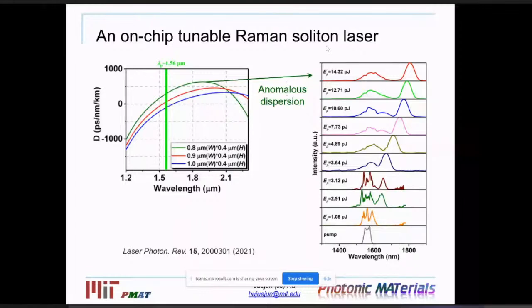And what happens here is that this ultra-short femtosecond pulse, when it couples to the waveguide, because of the large light intensity, starts to trigger stimulated Raman scattering. In the Raman scattering process, essentially you're converting photons of higher frequency to photons with a lower frequency.